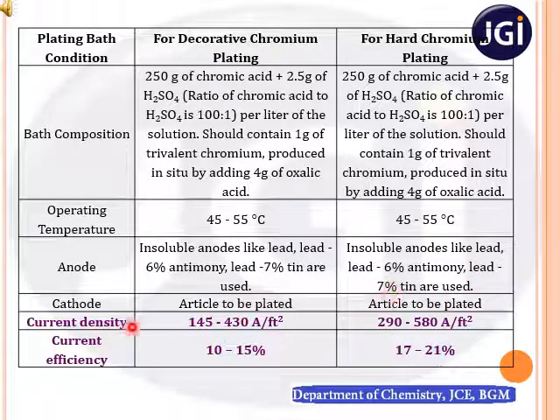Now we have two factors, current density and current efficiency, that play a major role in getting the required thickness. For decorative chromium, the current density maintained is 145 to 430 ampere per square feet, whereas for hard chromium it is between 290 and 580 ampere per square feet. Similarly, the current efficiency is 10 to 15% for decorative chromium, whereas for hard chromium it is 17 to 21%. By controlling these two factors, we can restrict the thickness of the chromium metal on the substrate surface.